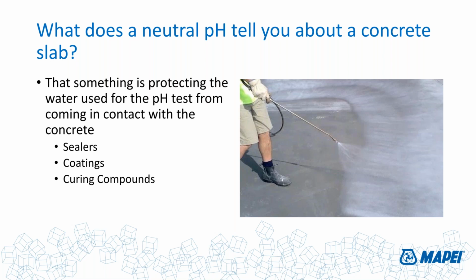contacting the concrete. Guaranteed 100% of the time, if you have an open concrete surface and you drop water onto it, something's going to dissolve into there and you will get a resulting pH. If, on the other hand, you've got a coating on top of it, you will get that neutral pH. So what would I do if I had a neutral pH in a concrete slab? I would abrade it, try to remove some of the coating on top of it, and redo the pH test, and 9 times out of 10, you'll get something between 9 and 12.